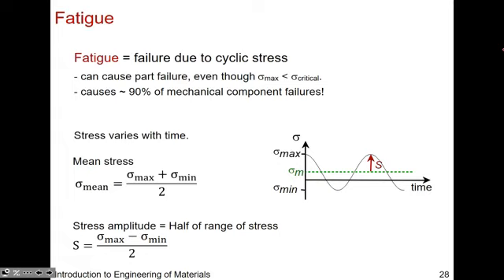And the way we look at fatigue and calculate it is we look at the mean stress. If you're applying your sigma, it could be in tension, it could be in compression. If we take the average of that, so we add the two together, divide it by 2, that's the mean. Then we can also take a look at what's called the stress amplitude, and that's the difference between your max and your min divided by 2. That's noted in the materials community as S, not sigma, S.